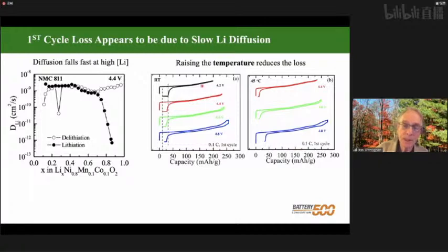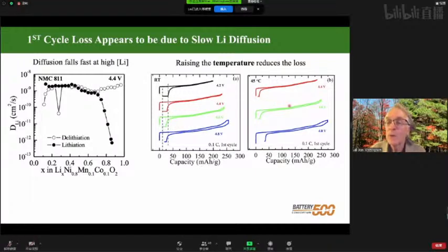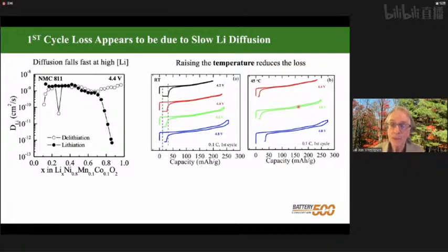And you'll notice the way we test for diffusion control, we discharge to 2.8 volts, then we hold it there for a few hours, and you can see we get more lithium back in all these cases. If we go to 45 degrees centigrade, now at 4.4 volts, you can see the first cycle loss is much less. We don't have to hold so long to get some of it back. At 4.6 and 4.8 volts, the charge and discharge curves are separating even more. So we're clearly out of the stability range of the electrolytes. So we're now restricting our cycling to 4.4 volts.